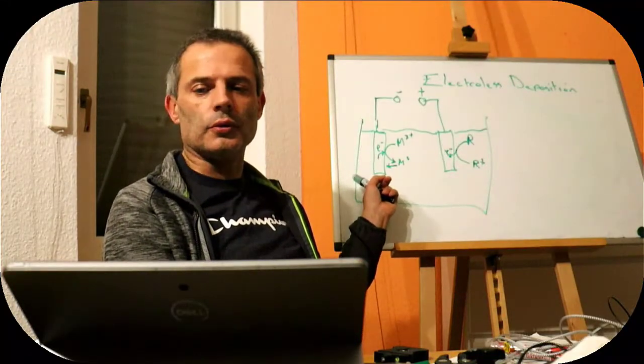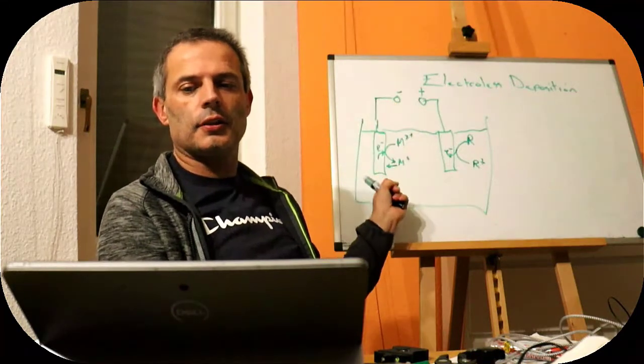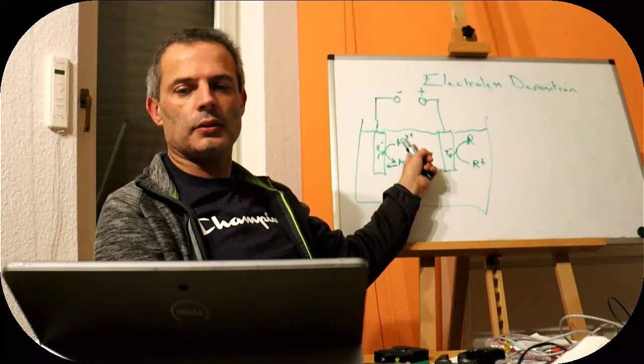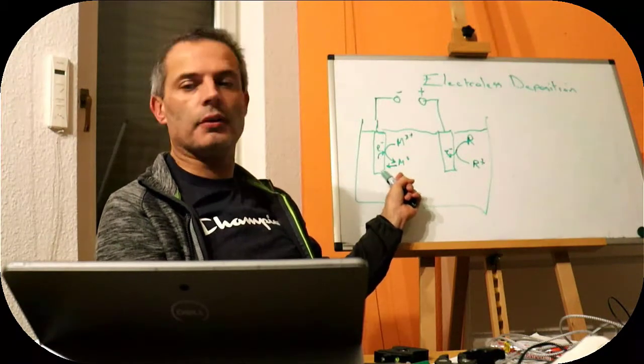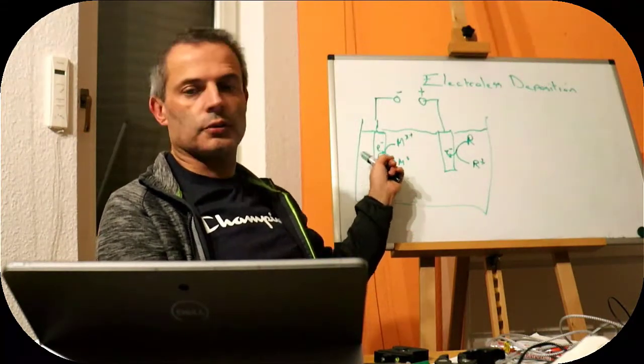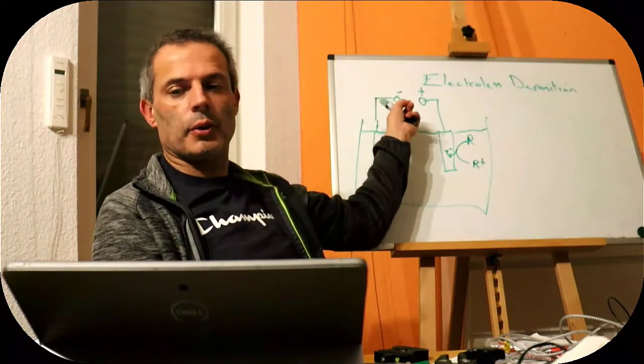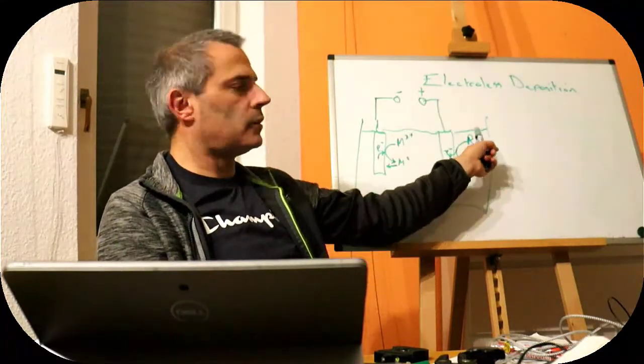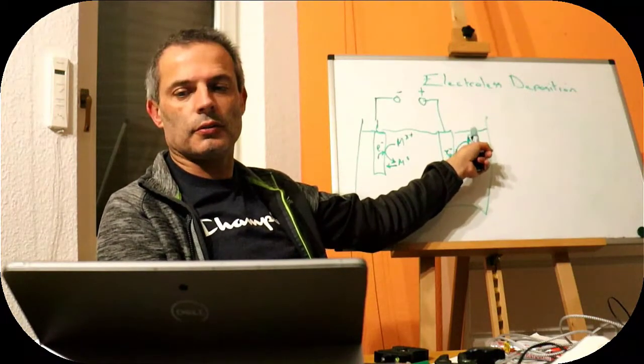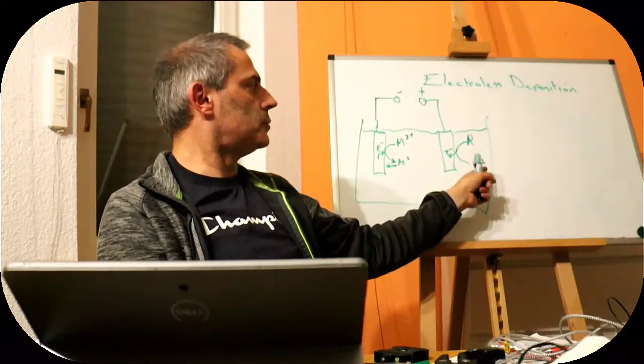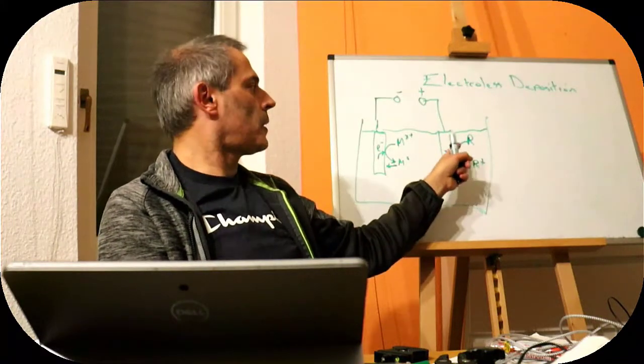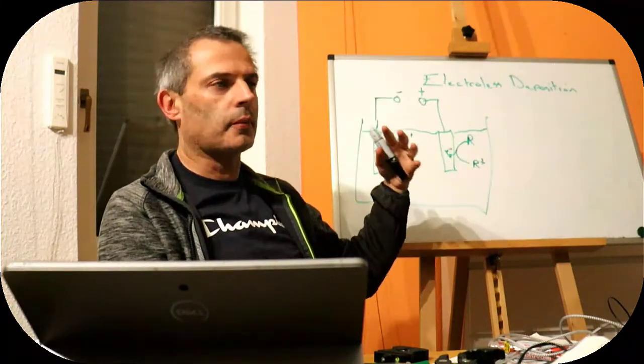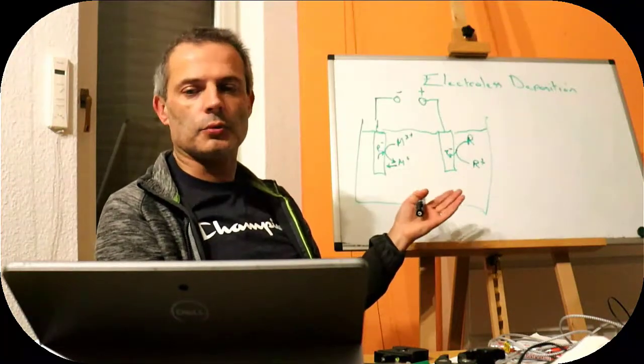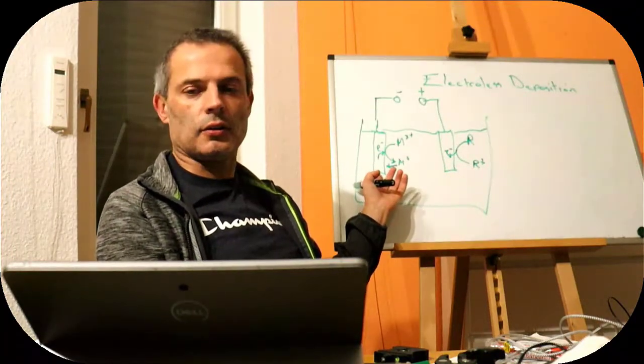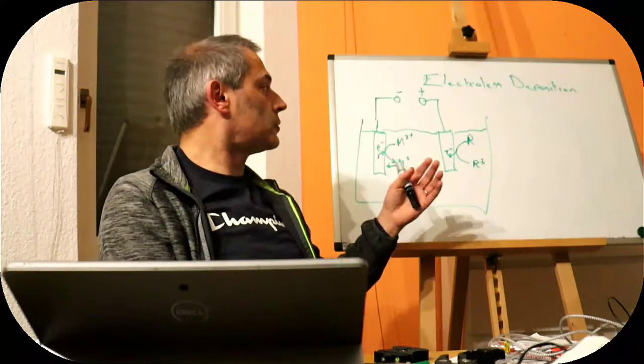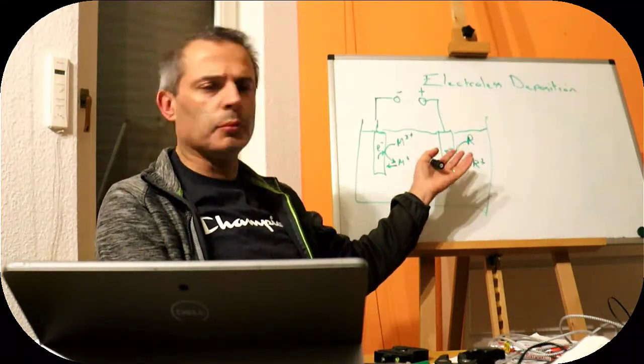We've got our electrode that we want to plate. We made it negatively charged, and it is reducing some metal ions from solution to metal zero, which sticks on the surface. Electrons come from the electrode, they have to come from the power supply, and on the other side we're oxidizing some kind of reduced form of some other chemical to an oxidized form, and that gives us some electrons. Typically we do this in the same bath, so in this case we might be making a metal on one electrode and oxidizing some water on the other electrode to make oxygen.